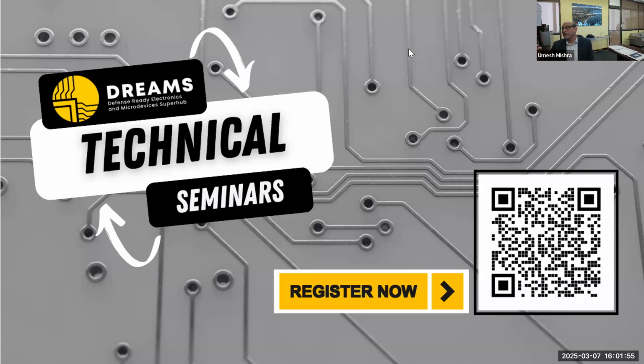I'll tell you basically what ends up happening. If you put GaN on top of AlGaN and keep growing GaN, for about 27% AlGaN, the amount of charge that's left behind is 4E12. So you start at, say, 8E12, you're down to 4E12. You've got to add 4E12 more charge, and you have to do it in a very small doping region to keep the aspect ratio right. The window just gets hard. It paints you into a corner. That's all. Okay, thank you.